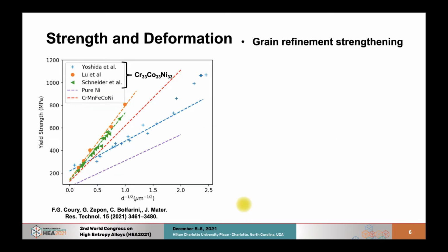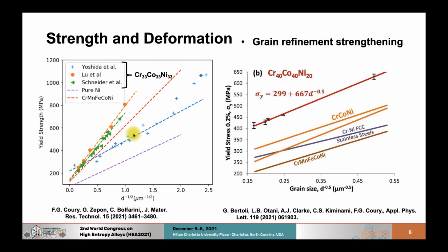So moving on to strength and deformation of these alloys, I'm going to start talking about tensile properties. And one thing on which these alloys show really promising results is grain refinement strengthening. So on the equiatomic chrome cobalt nickel alloys, we know at least three studies have been done to identify the Hall-Petch constants, so the effect of grain refinement on the yield strength, and they diverge. The studies give some reasons for that based on concentration of impurities, and we're going to talk a little bit more about this on the very last slide of this presentation.